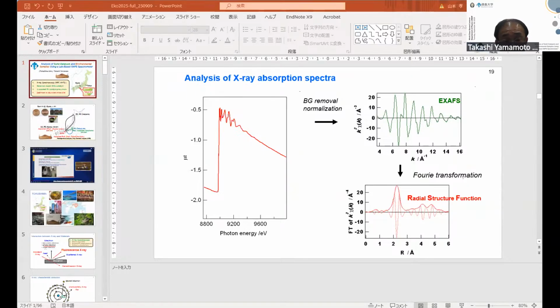Then we change to wave vectors like this. This is the XAFS spectrum. Next, we apply a Fourier transform to obtain the radial structure function. This is not exactly a radial distribution function, but a radial structure function. It reflects the coordination spheres, which may be around 2 or 3 angstrom.